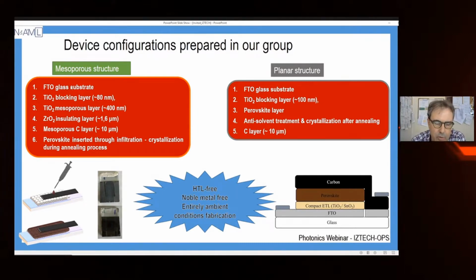We have a substrate of FTO. We have a titanium dioxide blocking layer. This is the relative thickness of the films. We have also a titanium dioxide mesoporous layer. Then we also use in that structure an insulating layer of zirconia, and then we put the carbon. The carbon is a mesoporous structure of carbon as a paste on the top.